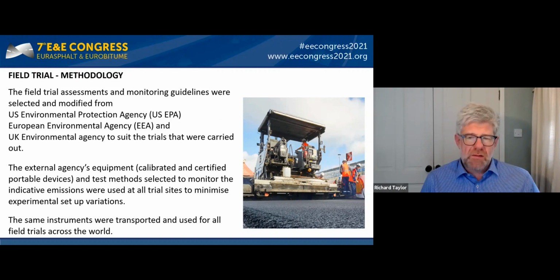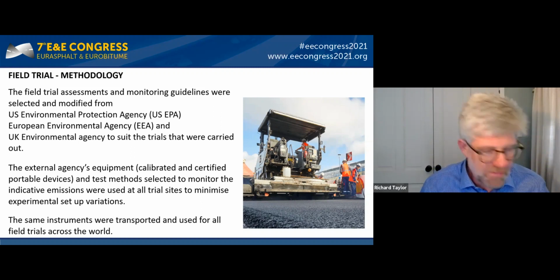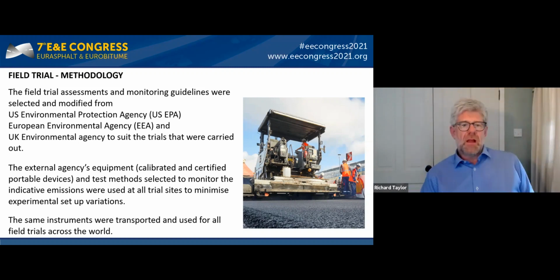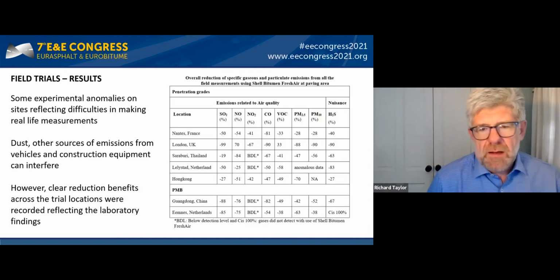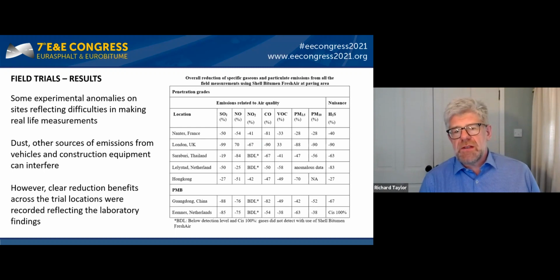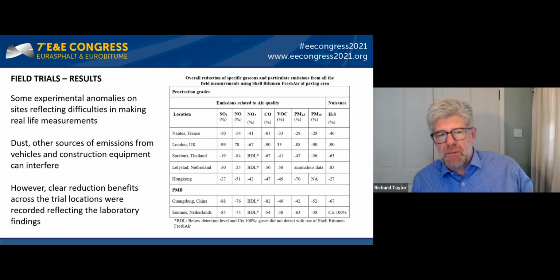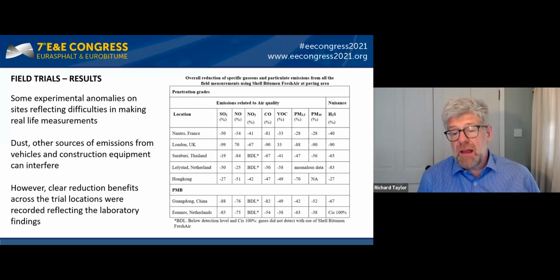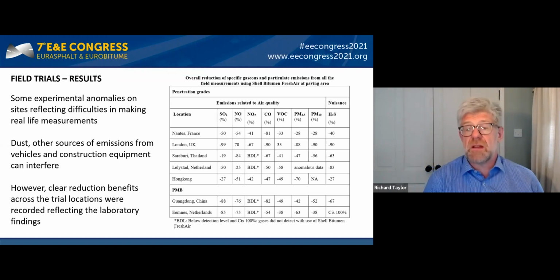So when we were trying to validate the findings from the laboratory in the field, we thought it was very, very important to take out as many variables as we could. And one of the key variables was simply the equipment and the instrumentation that we were using to make the measurements. And so from the field, a very, very encouraging set of data here from the real life emissions. As you can see, we had similar, fairly high levels of reduction from certain species.